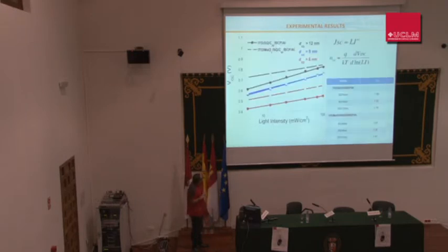And well, these are some physics parameters that tell you, for example, that the VOC goes linearly with light, so you can calculate the n value. It tells you about the number of traps in the bulk, and that's what you want to know. For example, if your device has 9 nanometers, your n value is over 2. n usually has to be close to 1.